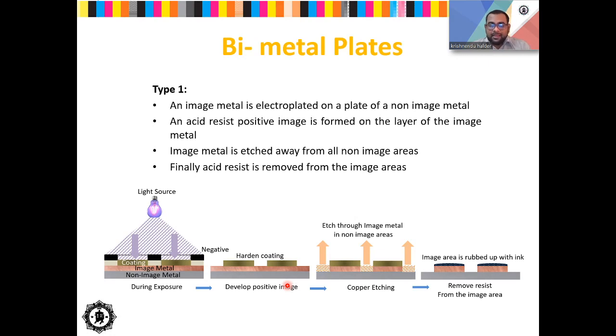So once you have etched, the copper will be removed from the non-image area. Obviously there is a certain consideration that has to be taken care of: during the etching, the etchant should not attack the lateral wall of the image area. That precaution has to be taken by the plate maker, as well as the timing required and the strength of this copper etching chemical, which has to be known. So after copper etching, what will happen?